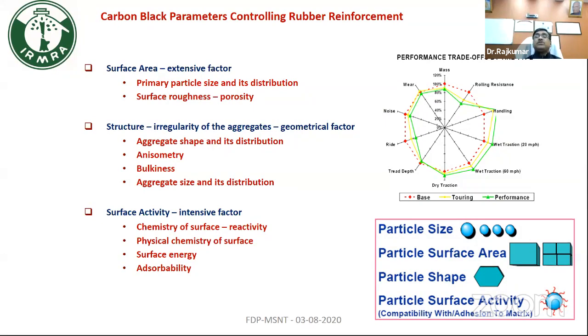Much more research is going on in this particular area. So in a tire compound, for example, lots of advancement has taken place: wet traction, rolling resistance, skid resistance. These are some of the areas where tremendous improvement has been found with the advancement in filler technology. Especially they play with the structure and surface area of carbon black, and they found tremendous improvement. Even with silica, nanosilica, and nanofillers, there are advantages.